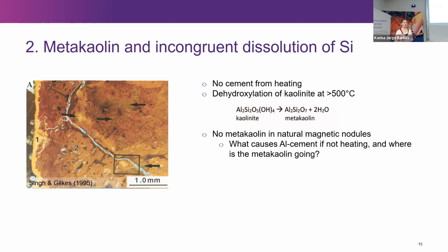I tried to crack a few open and they went flinging across the rock lab, and we found them a couple of years later hiding under a table. They're really difficult to break. They're filled with this aluminous cement that fills up all of the cracks in the pore space, and it's kind of glassy. Some people have identified it as a transition alumina phase. It's really difficult to identify, so some people just say it's a glass. But interestingly, I was not seeing this in samples that I popped in the oven and heated up.